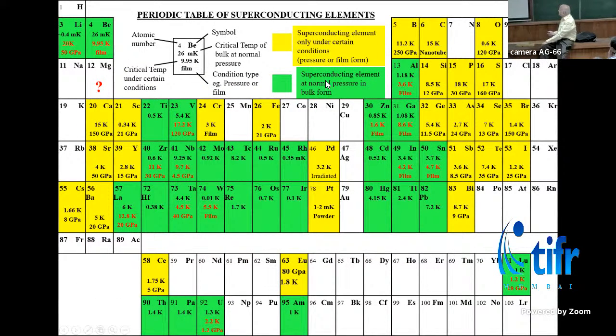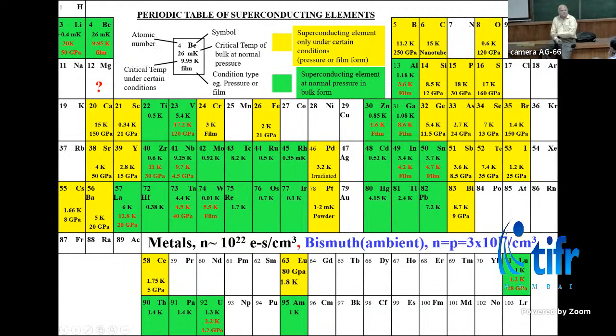So okay, let me come back to this periodic table again. So I told you this bismuth is something different from these metals. Bismuth has 5 orders of magnitude lower carrier concentration. So no sane person will tell you that bismuth should be a superconductor, because there's a prevalent notion that you must have high carrier density to get superconductivity. So then reluctantly people tried, because bismuth is a very nice thing, you can grow it very nicely. Then the Helsinki group went down to 10 millikelvin and they stopped. They said, okay, it's not going to superconduct. So they left it.